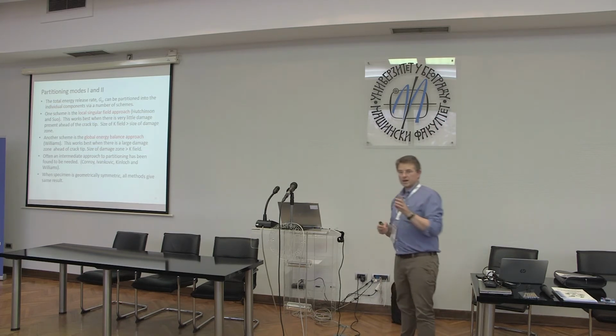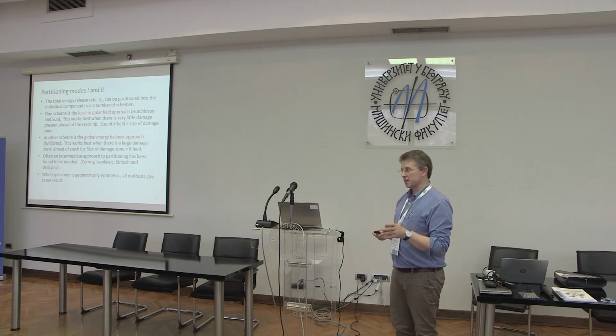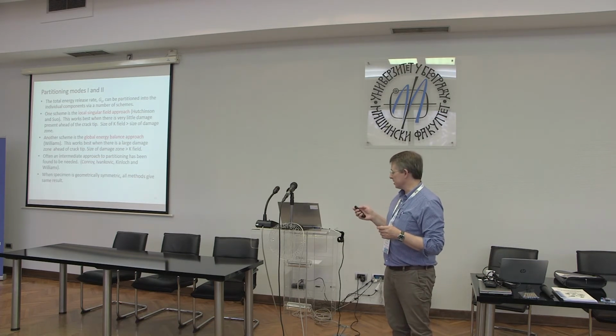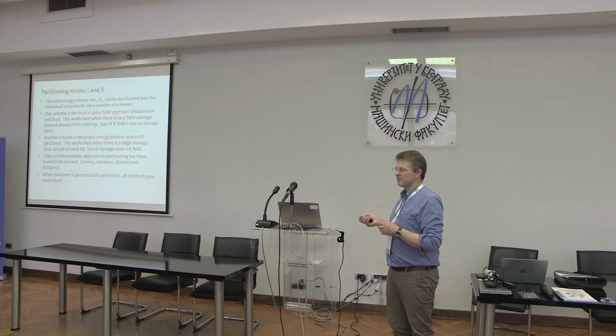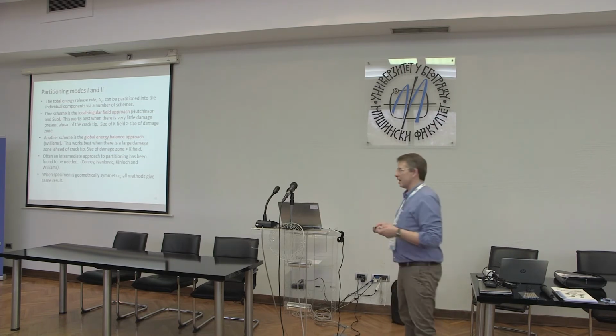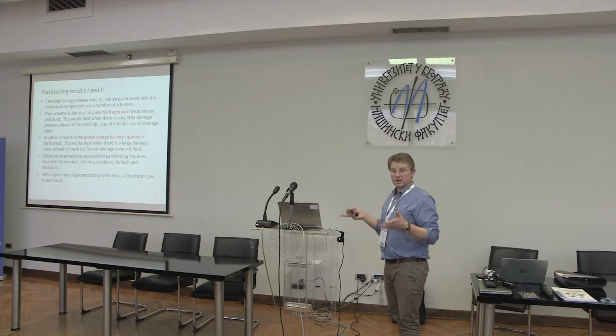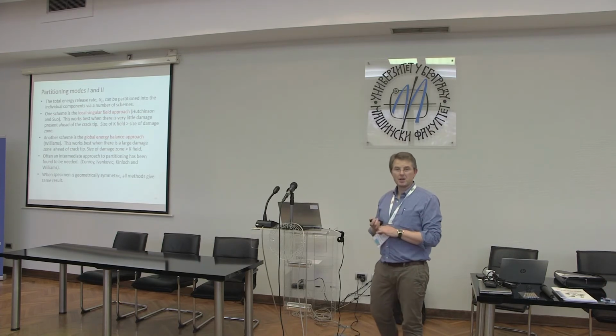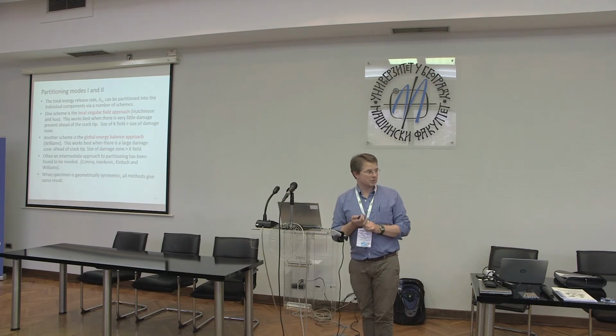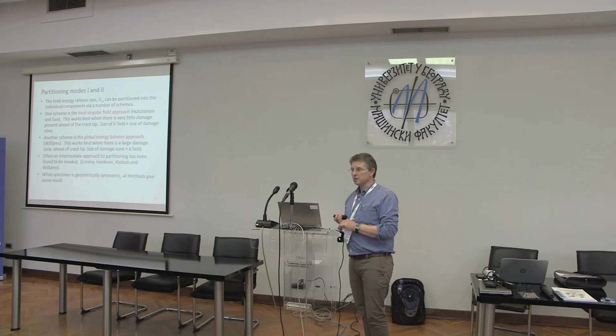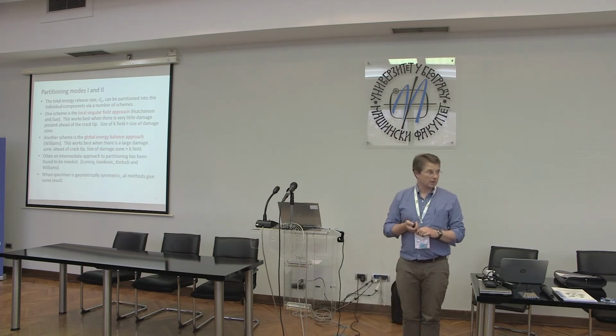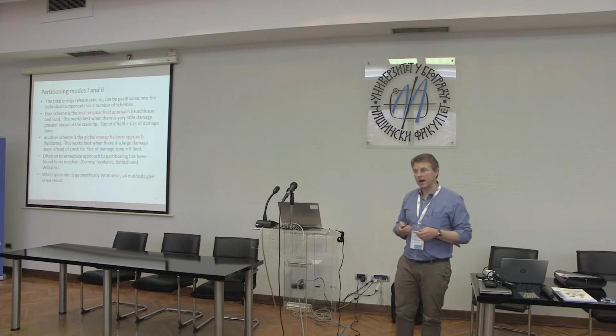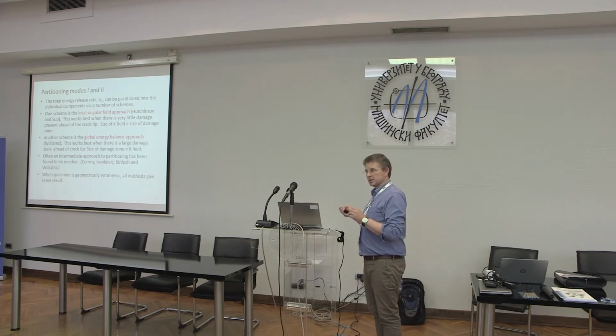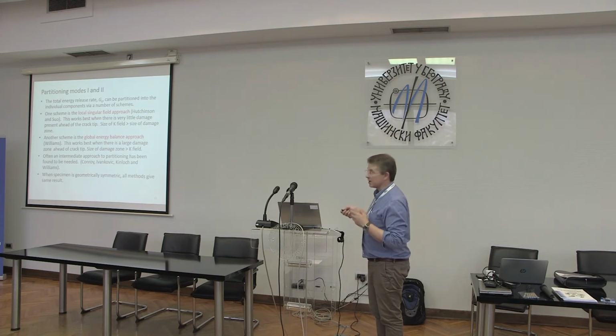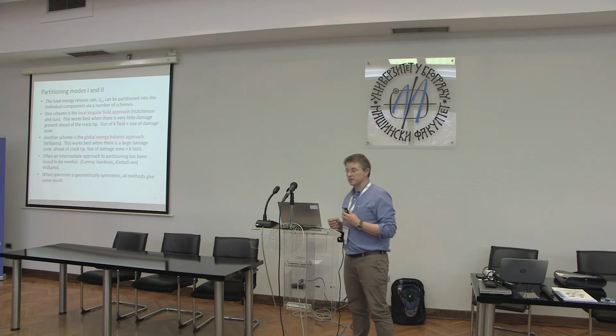Okay? Once you've worked out this factor of singularity, you can use that to accurately partition using a semi-analytical approach. And we use that on a number of systems. It works well. So I guess the takeaway message is if you find yourself needing to partition into mode 1 and mode 2, first of all, know your material. Okay? Know how much damage you have at your crack tip, and then select your partitioning scheme accordingly. Okay? So no one scheme, i.e. singular or global, works for all materials.